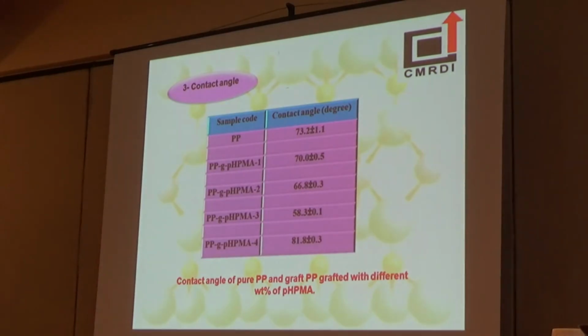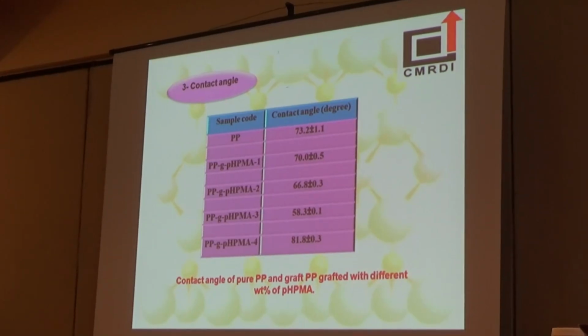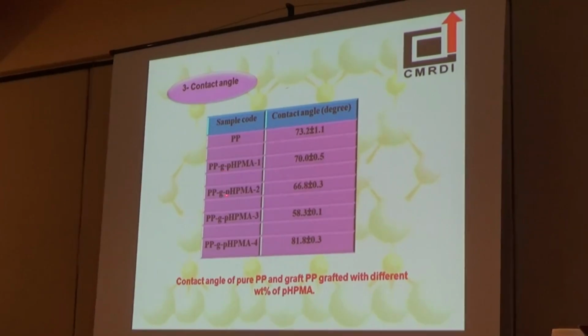The polarity of pure polypropylene and polypropylene grafted samples was measured by measuring the contact angle of distilled water on the surface of the prepared sample. It was found that the contact angle decreases by increasing the amount of p-hydroxy-N-phenyl maleimide monomer, which means that the hydrophilic character increases. But by increasing the amount of monomer to 4%, the contact angle increases again. This may be due to the non-homogeneous distribution of the grafted chains on the surface.